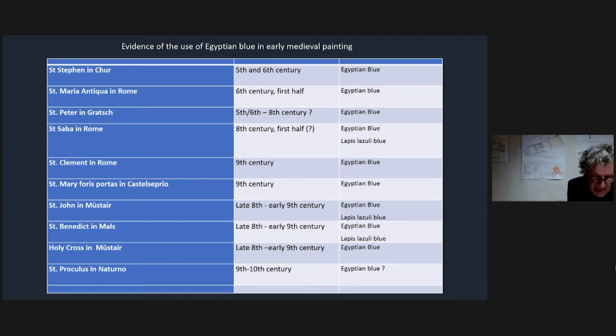Later, the first evidence concerned the wall paintings of the Church of San Saba in Rome, dating back to the first half of the 8th century. Here, Egyptian blue and lapis lazuli were detected mixed together in the same pictorial layer, as we shall also see in Müstair and Mals. These are the oldest Western paintings in which lapis lazuli was used as a blue pigment. There is still a gap for the use in fresco during the 7th century, but we have no fresco from this era.